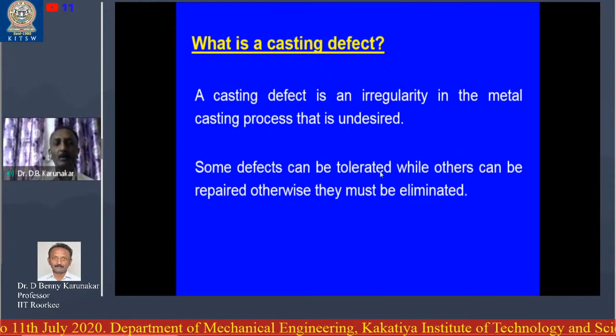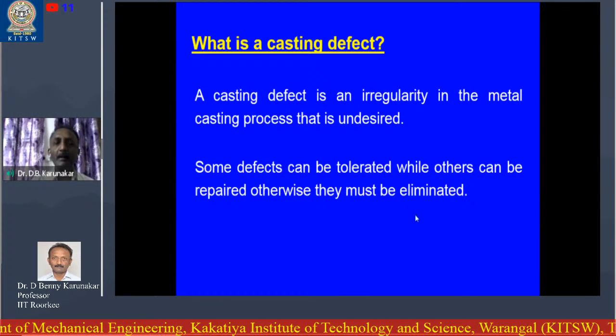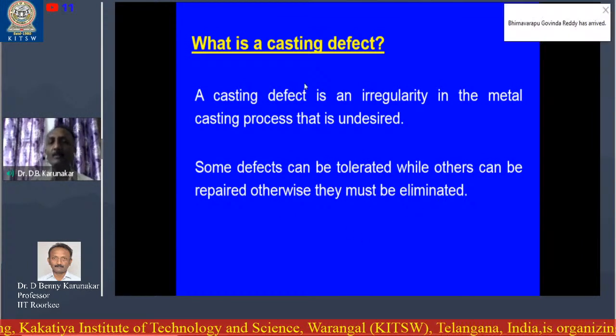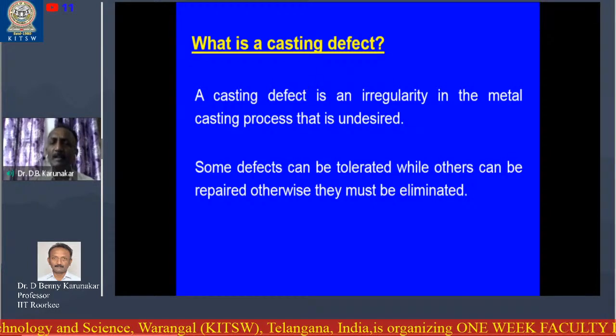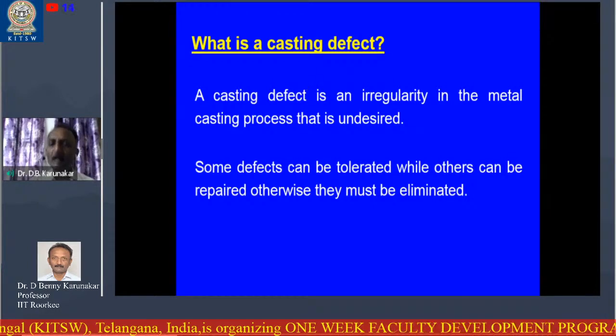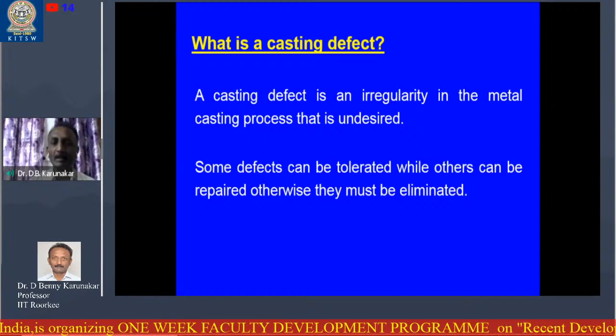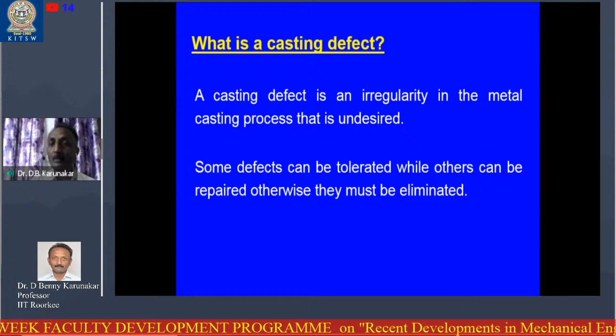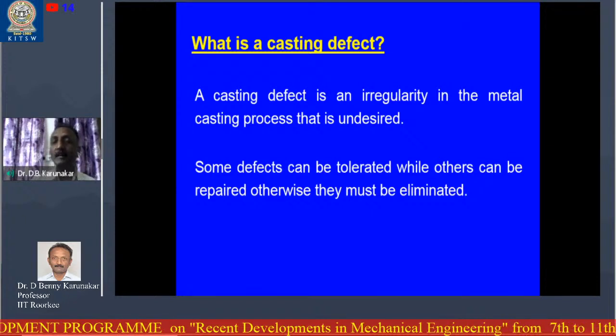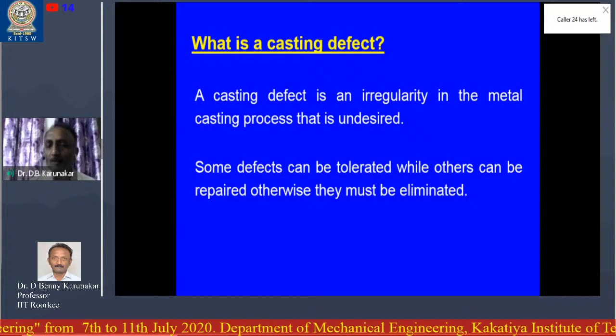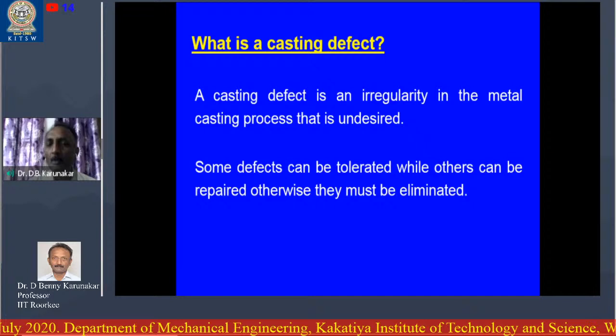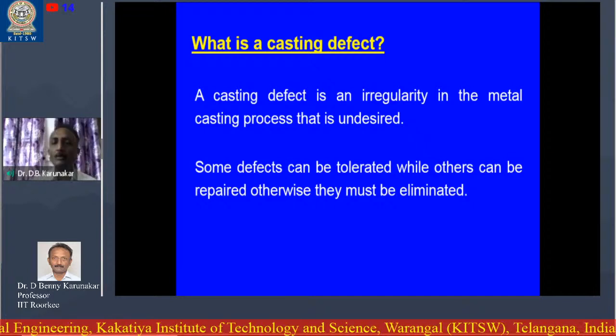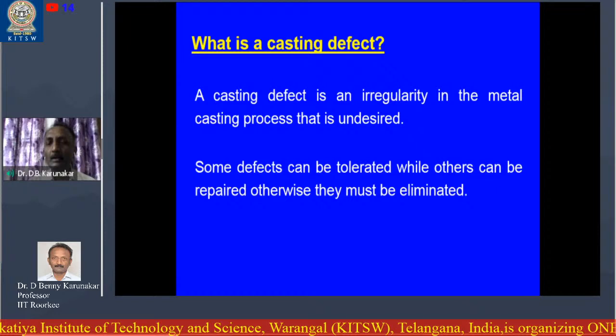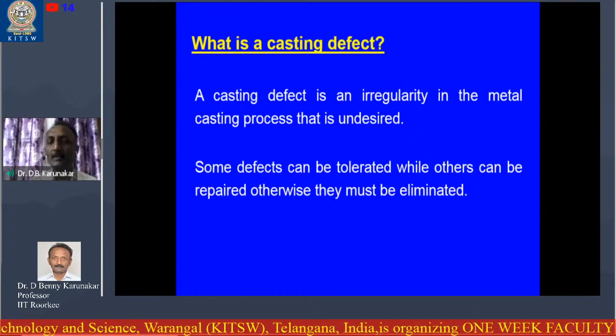Some defects can be tolerated while other defects can be repaired; otherwise, they must be eliminated. What does it mean? Some defects can be managed - even if the defect is present, still you can work with that, that is tolerated. Some other defects can be repaired - for example, on a big casting there is a small crack, so that can be welded, that is the repairing. Sometimes the crack is too big, or there is a severe shrinkage porosity defect - in that case, what to do? There is nothing we can do except that it should be rejected and melted inside the furnace again.